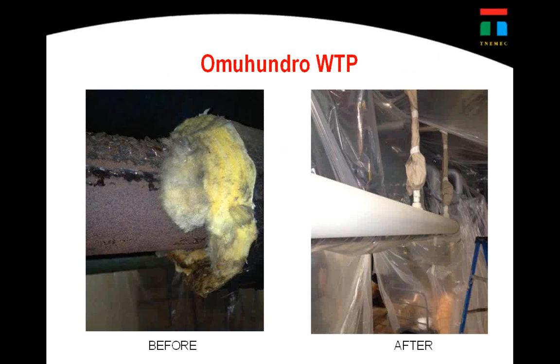So here's the kind of before and after of the corrosion of the CUI. So here's the CUI issue that they had, and the coating applied directly to the piping. Now, what this does in the CUI configuration is that you can actually see where your corrosion is going to occur now if you have a problem. Under the one on the left, you have no idea where the corrosion is taking place. You can see at the very top of the pipe there's a lot of heavy corrosion where sweating has occurred, and look at the mold that's growing underneath it in the belly of it.